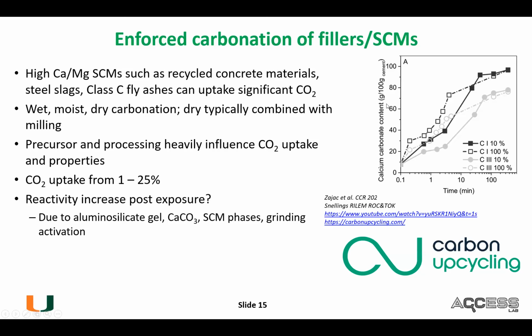And also, at least in some cases - remember we talked about supplementary cementitious material reactivity - it does seem possible that after the carbonation, the reactivity increases a little bit. And this could be because in some cases you form aluminosilicate gel, which is essentially amorphous silica or amorphous aluminosilicates. That's pretty reactive. Calcium carbonate also has some reactions in concrete, which makes it useful. So it could also just be that your original SCM phases are reacting.